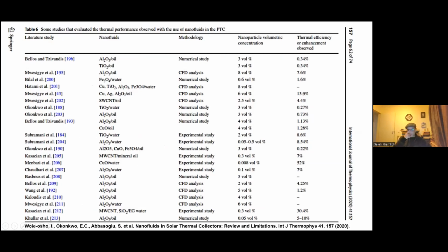From the literature, as you can see from this table here, borrowed from this paper, which was published sometime in 2020, it shows clearly that scientists around the world are working hard in order to enhance the efficiency of parabolic trough solar collectors. As you can see, they are using nanofluids here in general. I'm not going to read all of these, but I'm just going to take some cases. For example, there are people working on numerical studies, trying to use alumina with oil, titanium oxide with oil, at some, let's say, 3 volume fraction. Through numerical analysis, they found an enhancement in the parabolic trough collector of 0.34%, which seems small, but it's fine.